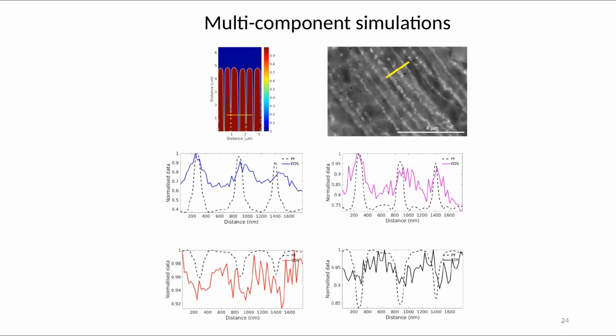So generally, there are 2 ways. If you are looking at only the gross estimates, like what would be the porosity or what is the susceptibility to cracking, etc., then there are some non-dimensional numbers that are defined. We will come to that in a moment. But if your idea is to understand the microstructural evolution, then you have to do it in 2 stages. Okay, you have to do first a simulation with the laser heat source, its motion, and the laser melt pool formation, etc. as a thermal simulation. From the thermal simulation, you should extract the cooling rate and gradient. And using those as the input conditions, then we do the microstructural simulation. Okay, so that approach of doing multi-scale simulation is something that I will be presenting in the end. We call it the ICME approach, so integrated computational materials engineering approach.